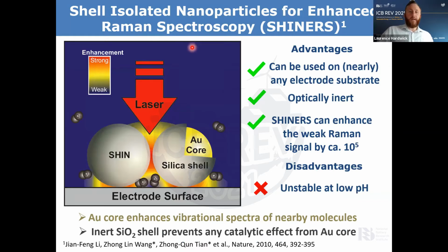So this technique that we use is shell isolated nanoparticles for enhanced Raman spectroscopy. We use these SHINERS particles, which have a gold nanometer core with a silica shell on the surface, and we can put these particles down on the electrode surface and use them to enhance the Raman signal at the electrode interface. So it can be used on any electrode substrate, and they can be optically inert, and we can get enhancements of around 10 to the 5 for this.